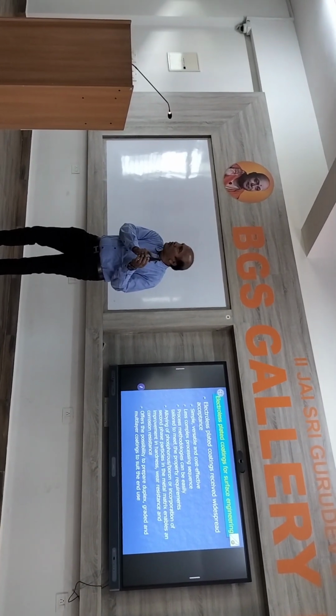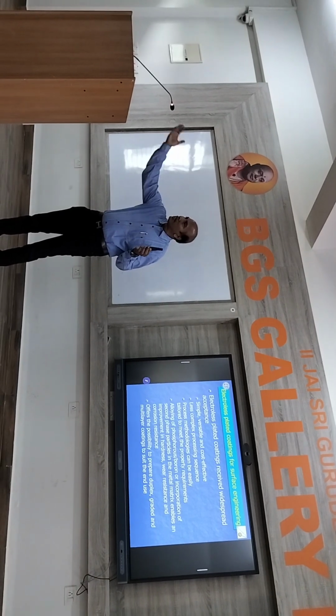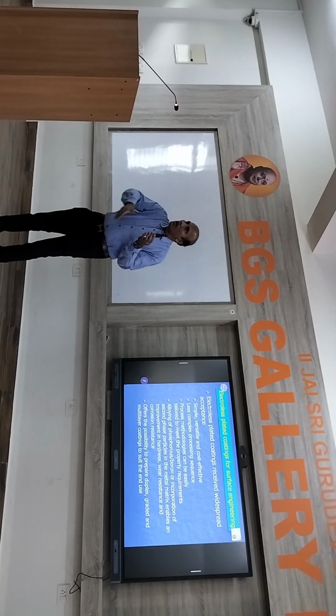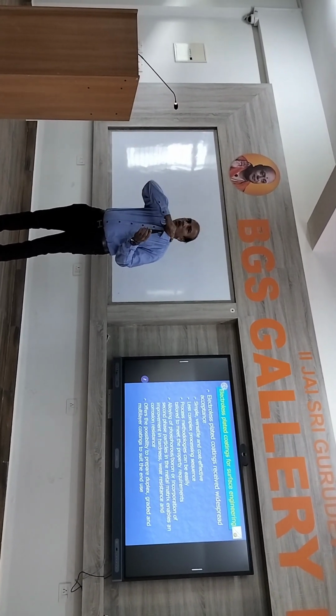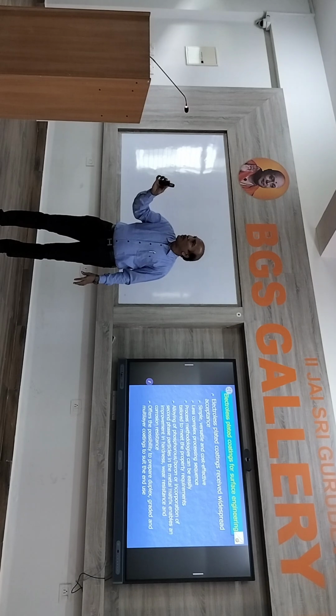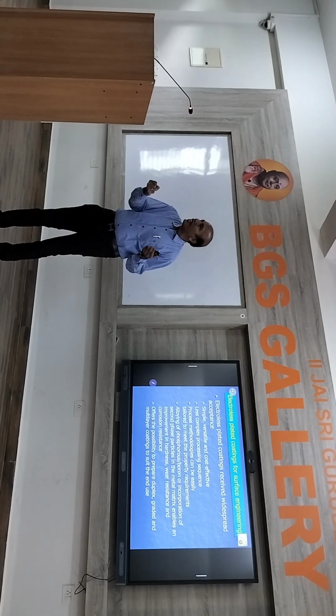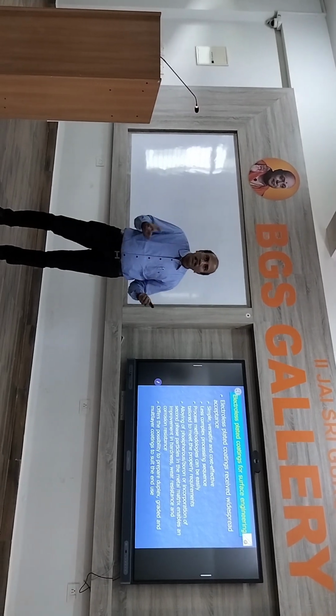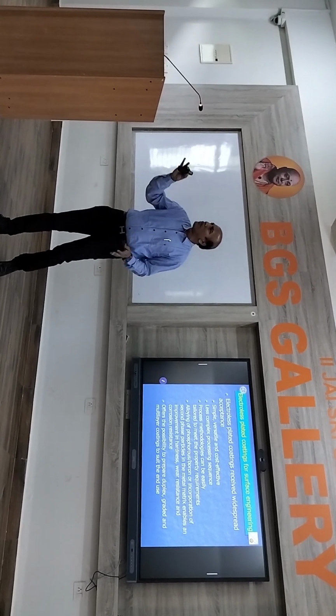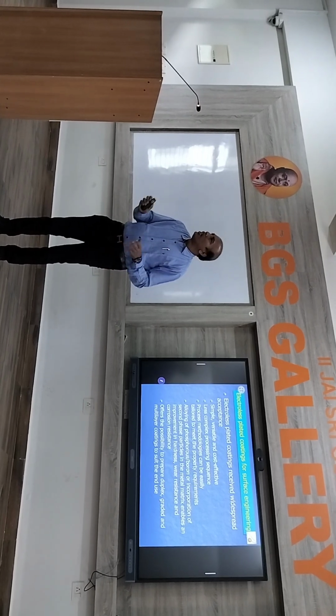So what I should do, even though I want 25 micron, but here it will be 5 micron, definitely I have to increase the duration. Instead of 15 minutes, I have to coat it for 1 hour. After that, another mechanical operation is required to remove the excess material. Here it is not like that. It is a simple chemical reduction process in which the metal source will be there. Apart from that, you have a reducing agent, and together with some complexing agents, buffering agents, all these ingredients, which are properly maintaining the pH and particular temperature, you will get a uniform coating because here there is no electrode there.